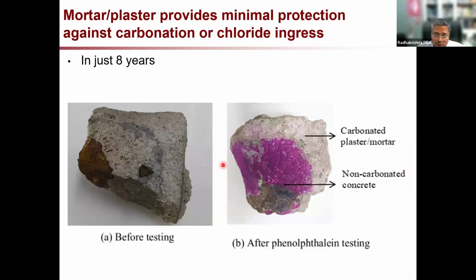Now, people might say that all the mistakes in the cover are covered up by putting proper plaster. This is a photograph to show you that plaster has no role in enhancing durability. It's just a cosmetic cover, only cosmetic. You see here, in one of the structures we visited, corrosion had already happened in 8 years after construction. We inspected and found that the concrete was very good quality, but cover was not adequate. And the plaster is completely carbonated. This is a phenolphthalein test. So plaster really doesn't resist anything, it just carbonates very, very fast.